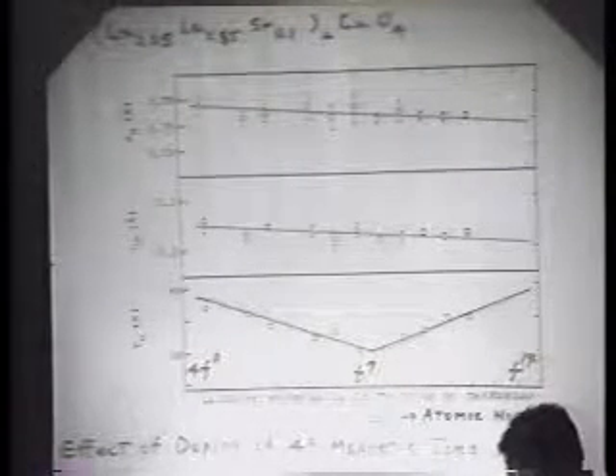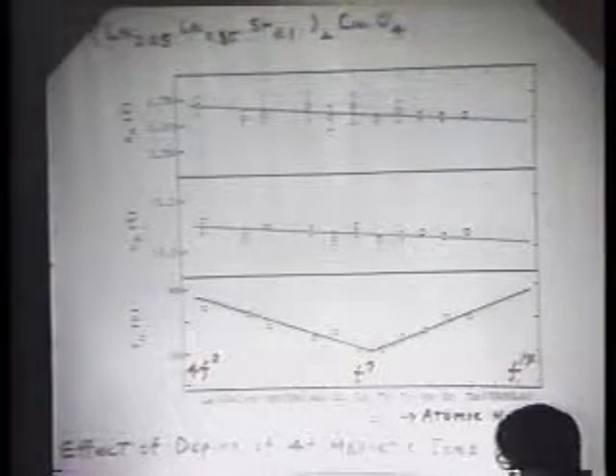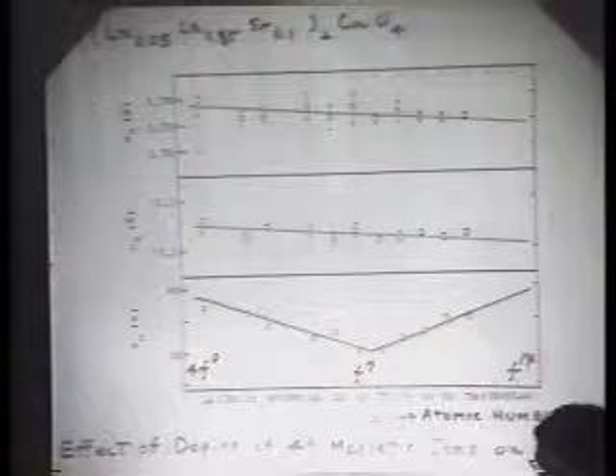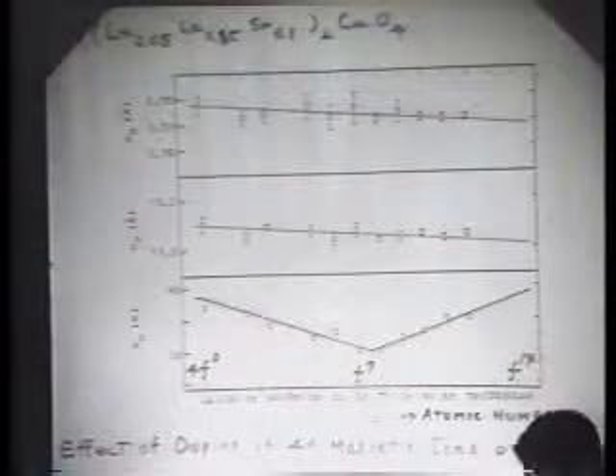Next one. Yes, such like that. Furthermore, we replaced lanthanum partly by rare earth elements. These results indicate that the depression of critical temperature depends on the concentration and total spin of the rare earth element. You see, gadolinium gives the lowest critical temperature. So this suggests that the spin exchange interaction with conduction electrons is effective on the critical temperature.